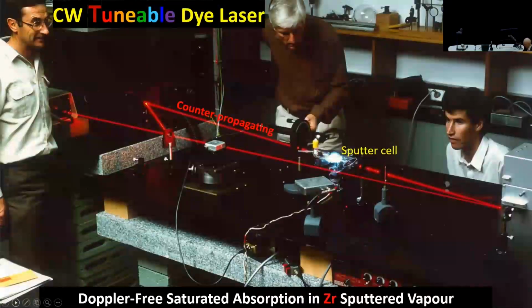So the next step was to go from pulsed lasers to CW lasers, which came on the scene somewhat later. And we wanted to be able to do a Doppler-free saturation spectroscopy experiment. So here you send one beam in to your sputtering cell, your vapor here, and you beam split and send a second beam in the opposite direction, so that both beams only interact with those atoms with a 0 velocity component in the plane perpendicular to the laser beams. So the atoms are interacting with both beams. In order to do that, they must have a 0 velocity component. They don't have a 0 speed, but a 0 velocity component.